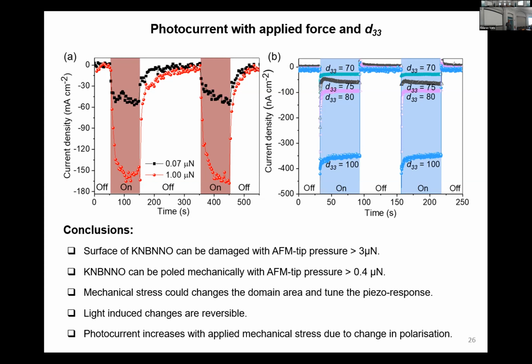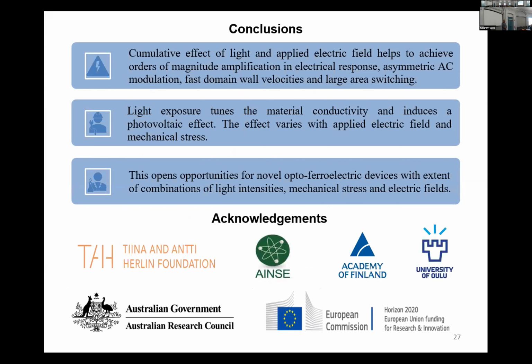So from this, what we can conclude is that a higher force can damage the sample surface. The material can be poled mechanically with loads of 0.4 micronewton, which is very low. Mechanical stress could change the domain area and tune the piezo response. Light-induced changes are reversible, and photocurrent increases with applied mechanical stress. So we can modulate the photocurrent with applied stress, or the other way around. So with this, I conclude this talk.